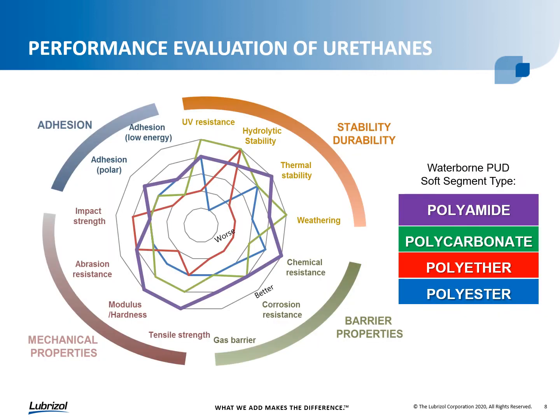When we compare the different soft segments or polyols in a base PUD formulation, we can start to see how the polyamide really gives you some distinct performance advantages over the other available polyol types. And you can see in this spider diagram, when we look at kind of 4 key areas of performance, be it adhesion, stability and durability, barrier properties, and mechanical properties. And you can see there's a number of different things within each of those categories. While the other polyol types give you maybe some solid performance in one area, they tend to fall short in another, where they might have really good UV resistance but poor hydrolytic stability. The polyamide gives you, I would say, better all-around performance.